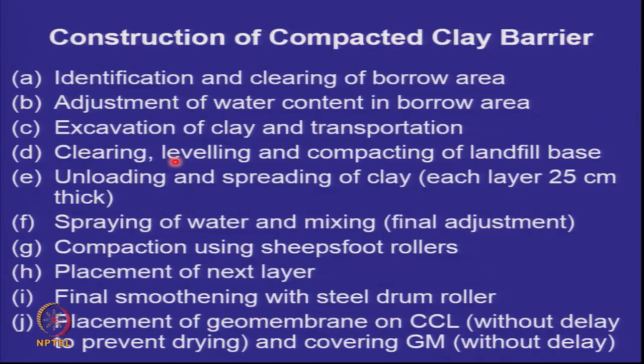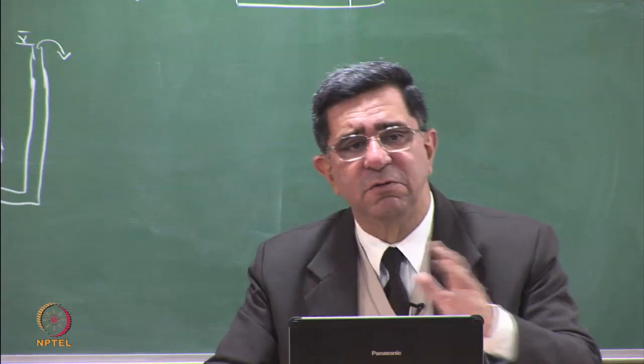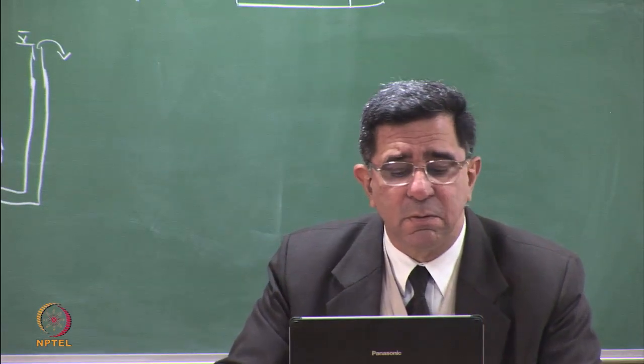So if you're going to add bentonite, 5% is sufficient for the purpose of getting low permeability, but it must be mixed very well and you'll need higher percentages of the other material depending on its plasticity. So in this way, I can find out the additive content. Then I have to construct the clay barrier. We've done the lab studies. So we identify the borrow area. Suppose I'm only using a compacted clay barrier, then I adjust the water content in the borrow area. Suppose the soil is totally dry, I can do some sprinkling there so that it's close to the optimum moisture content.